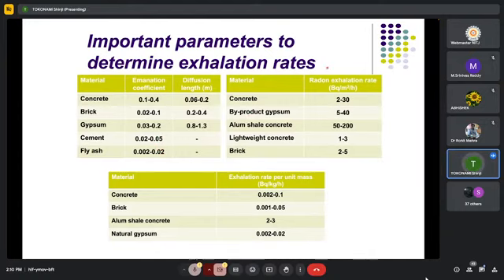Then this is a typical exhalation rate from various building materials. In the case of concrete, 2 to 30 becquerel per square meter per hour. The surface radon exhalation rate. Byproduct gypsum 5 to 40. Alum shale concrete 50 to 200. Lightweight concrete 1 to 3. Brick 2 to 5.